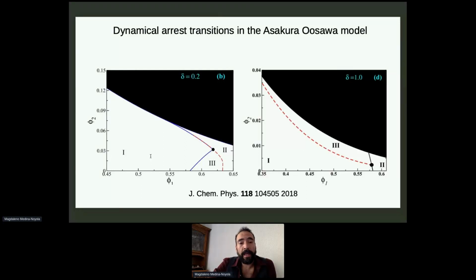For instance, for a large degree of asymmetry, it predicts some sort of topology which looks like the dynamical arrest scenario for the binary mixture. This line in blue that we are seeing here describes the dynamical arrest of the large species, which is the colloid in this representation, and the theory still predicts a region, in this representation with the polymer concentration and the colloid concentration, in which the colloids are expected to form a glassy matrix in which the polymers can still diffuse.